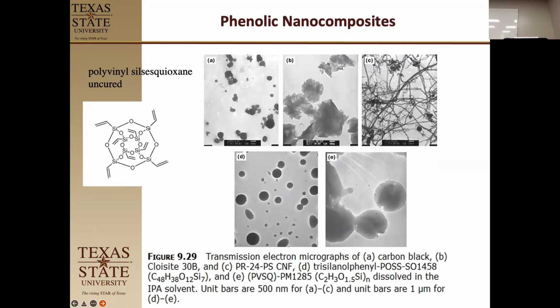This is carbon nanofibers right here, commercial grade carbon nanofibers. This is the one with the POSS. Notice the globules here. We have phase separation. POSS is phase separating out of the phenolic material. And then when they dissolved it in IPA, they actually saw, again, phase separation, a difference in that system.